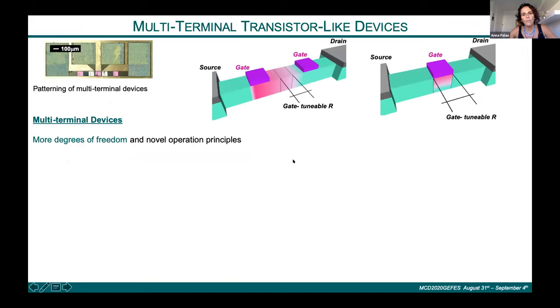What we have performed in the experiments is to pattern a YBCO layer. This is a SEM image which has been colored in order to show the different contacts. We have a four-contact configuration to test different places of the material, and also we have different gates. This is the bridge of the YBCO that we use, and we put different gates at different places of the bridge. In this configuration, we will evaluate what happens if we produce switching by using one single gate or two different gates.